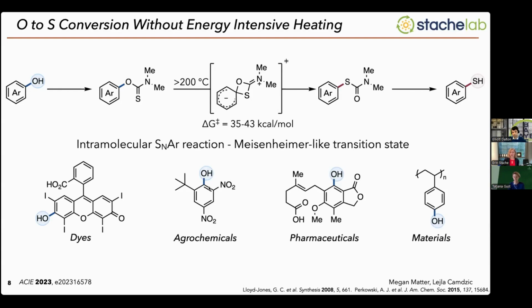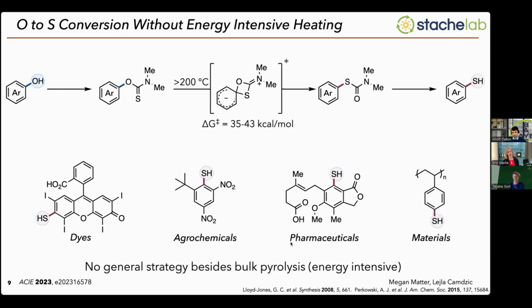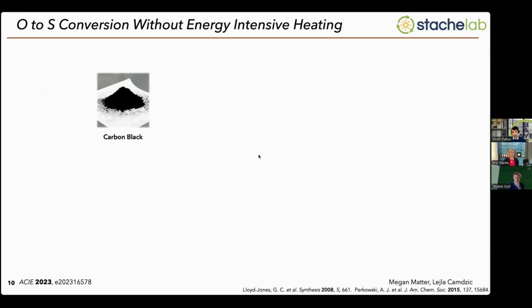And so this is a really useful reaction because you can think about all the phenols that we have in our commodity chemicals and pharmaceuticals and materials. And you can very simply convert these into thiophenols and get new chemical structures and new material properties. But there's no strategy to do this besides bulk pyrolysis, or no general strategy. Essentially, you need to overcome these activation barriers by heating these reactions to very high temperatures. And so we thought that we could use photothermal conversion to overcome these limitations. And we started by using carbon black.